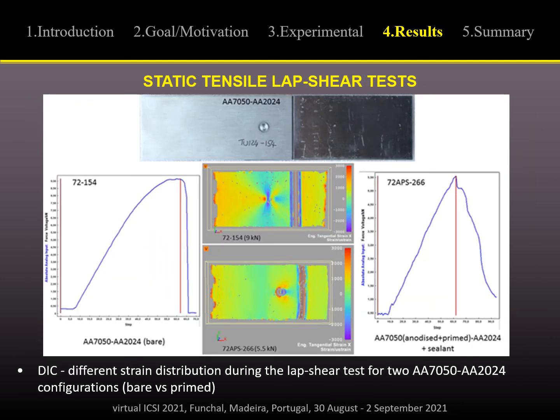A worse behavior of the primed configuration was confirmed also by means of DIC measurement. You can see a comparison of the DIC maps during the lap shear test for 2 7050 and 2024 configurations, so bare versus primed, and you can see a different strain distribution around this weld joint, where there is a typical butterfly shape, whereas in the primed configuration you can see only stress concentration or strain concentration around this weld zone.